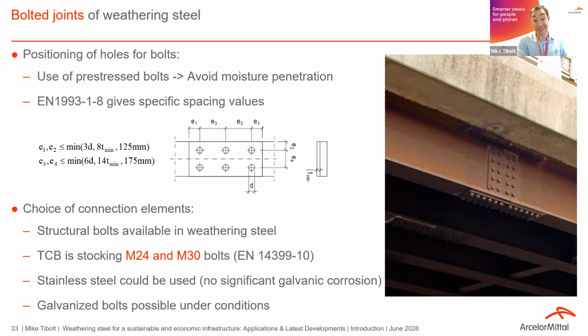You could also use stainless steel bolts, because the mass is quite small compared to the mass of the whole steel girders, so that no significant galvanic corrosion occurs. And under some conditions, you could also use galvanized bolts. Here, of course, you have to pay attention that you close and seal the connections, so as not to have crevices where water can get in. Otherwise, you have galvanic corrosion from the galvanized bolts toward the weathering steel, so the zinc layer will be consumed.